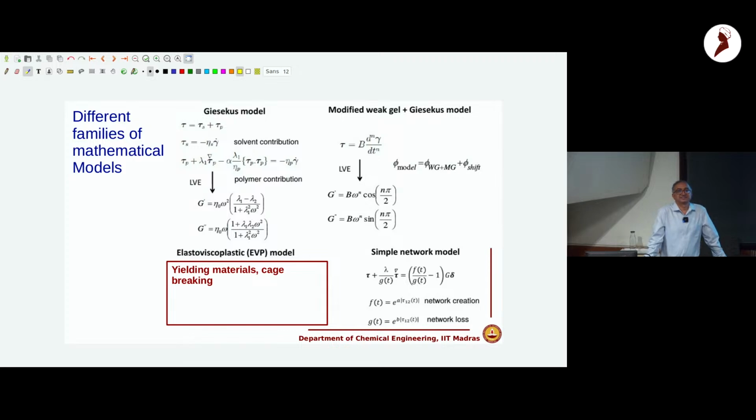No, so yeah, there's a guideline. Generally you would assume that the third harmonic is 0 in linear. It's very small compared to your first harmonic. When I see noisy data, even for a linear response you might get 5%, 2% third harmonic relative to the first, so that's within the noise of the system. Only when it gets to 10% or higher might you start seeing it contributing more. It's subject to the experimenter who is doing this. Yeah, absolutely, and the material system. No hard and fast rule.